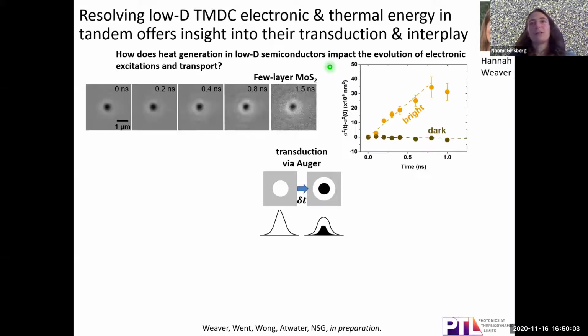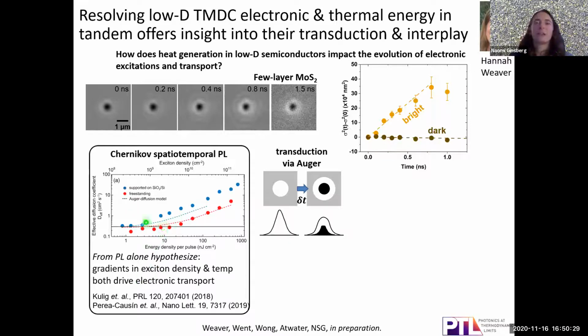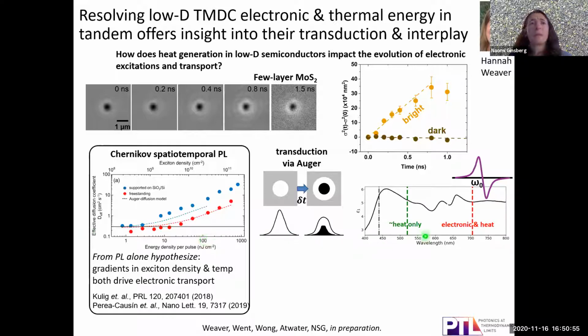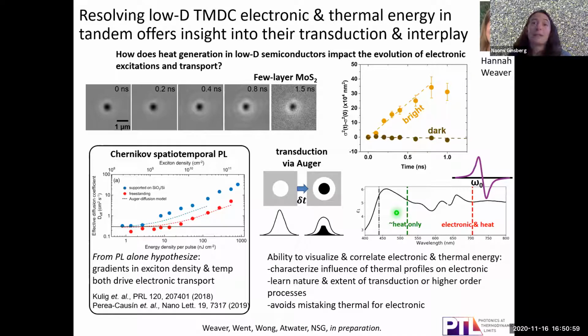So in few-layer transition metal dichalcogenide molybdenum disulfide, Hannah imaged a rapidly expanding positive contrast signal that's consistent with the diffusion of electronic species, and the negative signal you see is basically stagnant on these similar timescales, which we expect is dominated by heat. This is especially valuable because others, for example, Alexei Chernikov's group, have hypothesized from spatiotemporal photoluminescence, where they can only see the electronic contribution, that thermal gradients can drive excitonic diffusion, and show that these effects kick in at extremely modest densities. So now we can see the heat, plus we can see it in tandem with the electronic signatures. And it also appears that we can spectrally isolate the heat in order to fully dissect the interplay of these two different forms of energy, and also potentially to learn more about the Auger dynamics themselves.